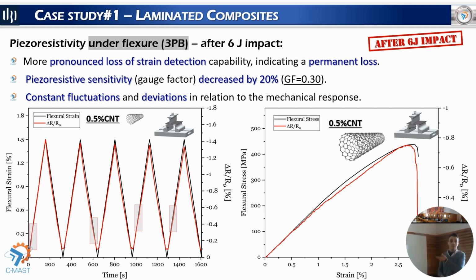In these impact tests, we saw in the microscopic image that severe damage was imposed on the samples, and here the deviation is even higher. Here we are in the cyclical tests, below or inside the elastic region of the sample, but we can see deviations of the electrical signal from the mechanical one during the cyclical tests, which means that severe damage was imposed on the samples. And here in the monotonic test it is even more evident. A lot of noise during all the experiments is a signal of mechanical damage.